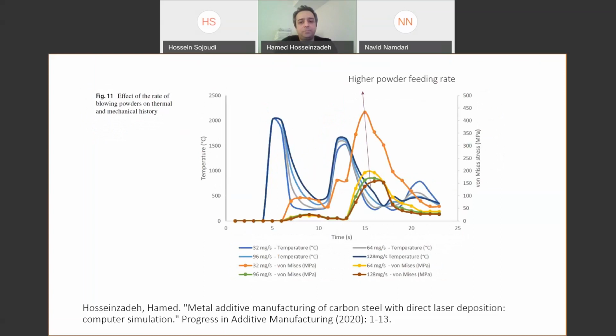We can also take the rate of powder feeding. If we increase the rate of powder feeding, it means that we have more heating, and so you can see that we have a higher level of stress in the sample. In general, it is a computational method, which is the only one for the large sample right now, and we can simulate the process of the DLD method and check the effect of different variables to see what would happen to the total distortion and residual stress if we change scan speed, laser power, and so on.